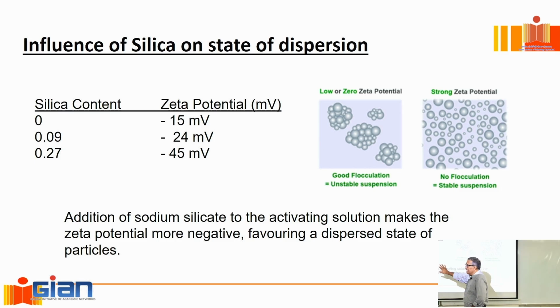When the value of zeta potential is negative, it will stay in a highly dispersed state. So what have we done here? We've added silica to the solution, and then we've introduced the fly ash into the solution. When we measured the zeta potential of fly ash in water, it was negative. The minute we added silica, it became even more negative. That means it's going to be highly dispersed, like individual particles. That's what silica does. It disperses them.